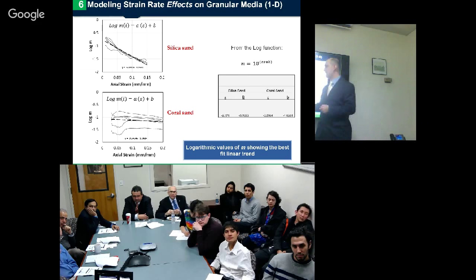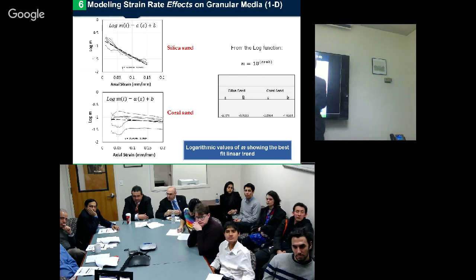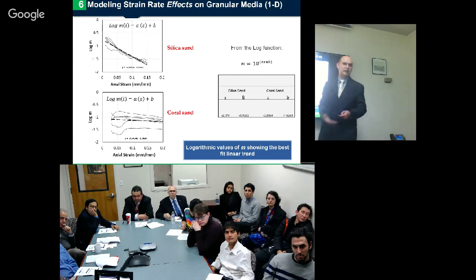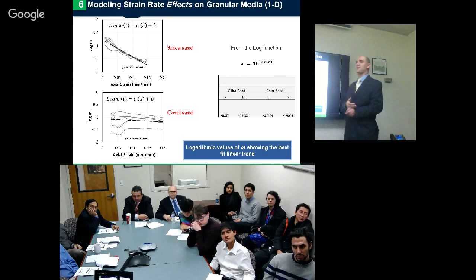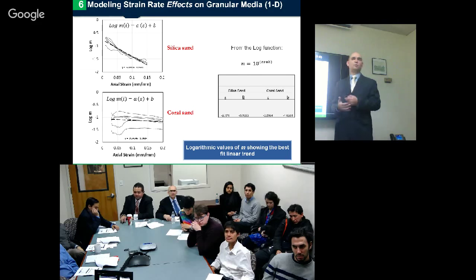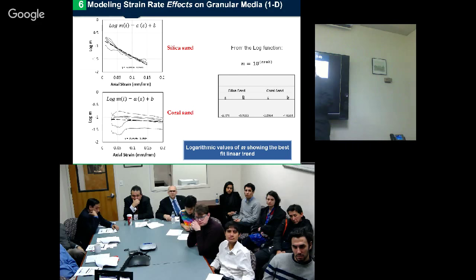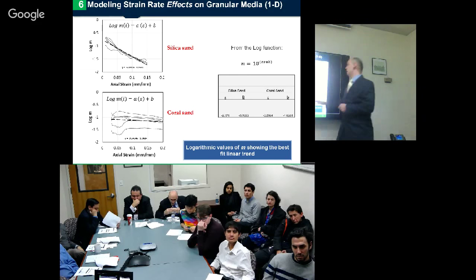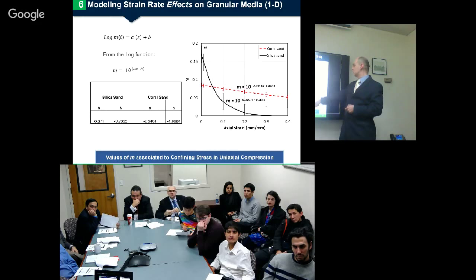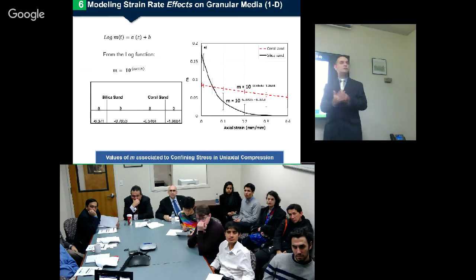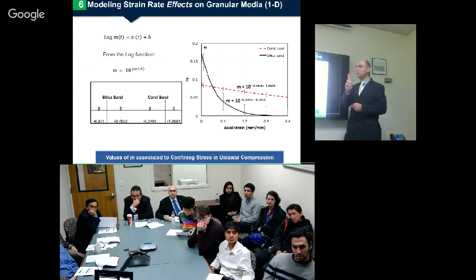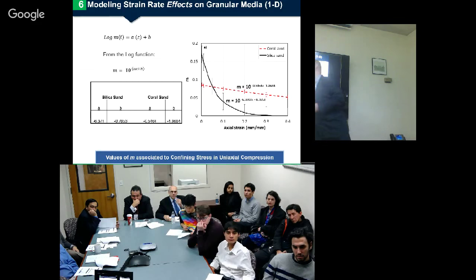For this material, for silica, for example, I found this relationship with m, which is a function of axial strain, or we can call it porosity. We can call it also void ratio. And by fitting a linear term here, or a log term here, we find out values of A and B for this function. And now this m value is going to go back, and then we remove the log, and we get something like this. Two different curves for coral and silica sand with two different constants, A and B.